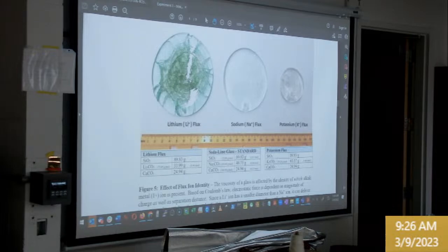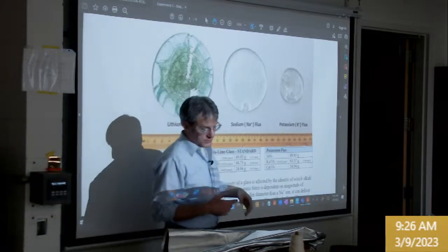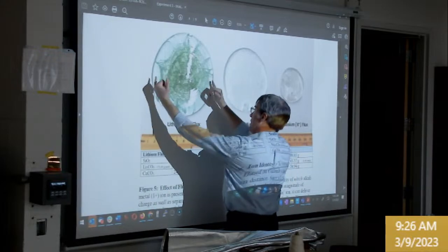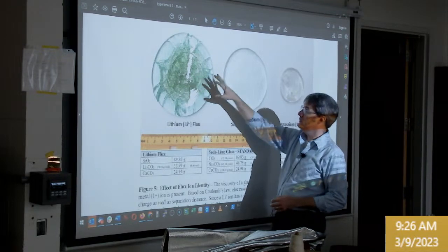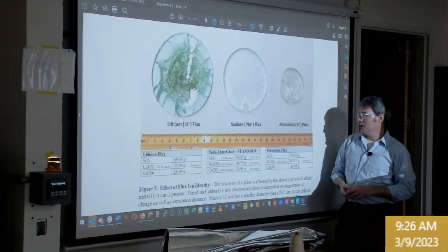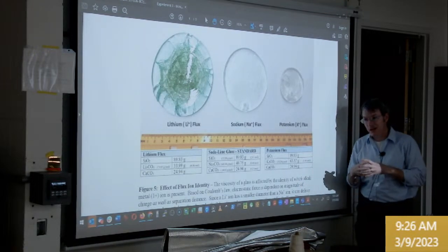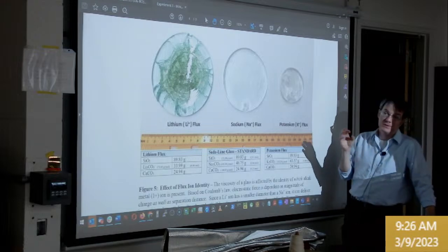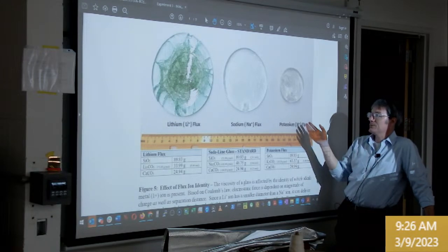We're not using lithium fluxes in the new furnace because it rips up the bricks and messes things up over time. But we have some representative samples with pictures and scale bars, so you can approximate and benchmark that behavior. We got a lot of glass out of that crucible. This is more typical for soda, sodium fluxes. Potassium fluxes don't flux as aggressively at all, and they often make a tighter glass at this pouring temperature that usually cracks and explodes. That's the reason we're not using potassium flux: they're unstable glasses. But you can use this to benchmark.